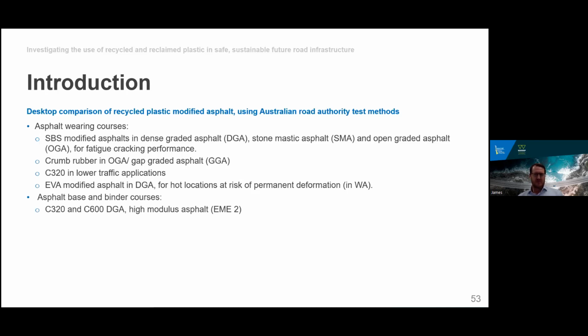There's some use of crumb rubber in both open graded asphalt and also gap graded asphalt in both Western Australia and Queensland. And there's still some use of unmodified C320 binder in asphalt in lower trafficked applications. One other thing to note is that in certain hot locations that are of considerable risk of permanent deformation, and in particular in WA, EVA modified asphalt is sometimes used in dense graded asphalt. So in terms of Australian context, EVA would be A35P binders.